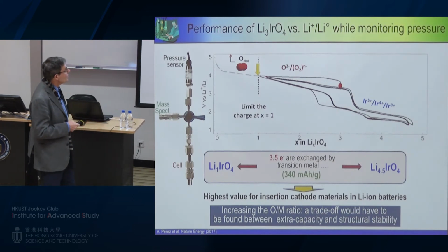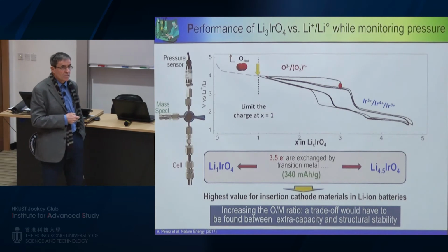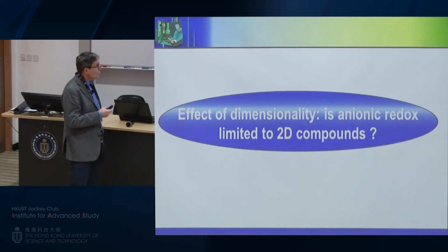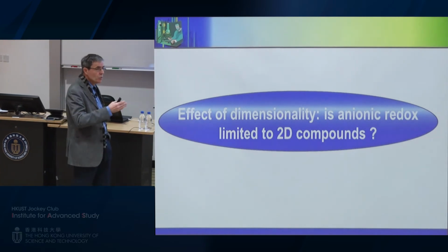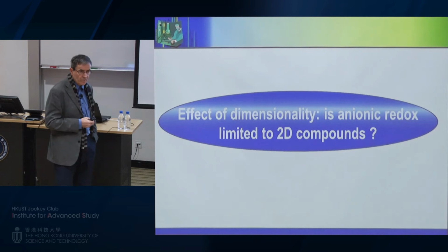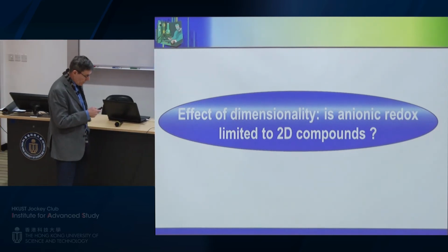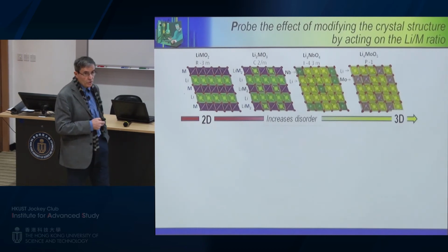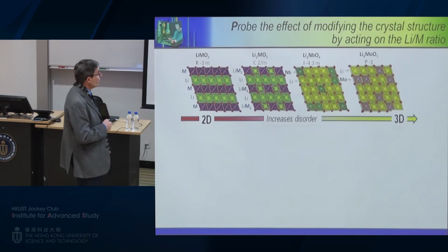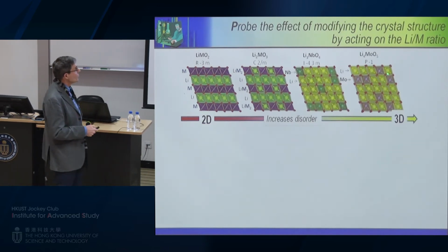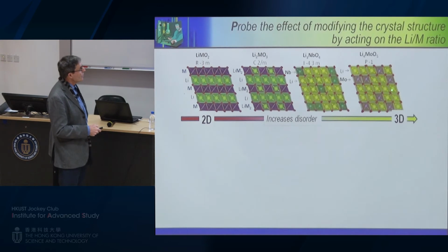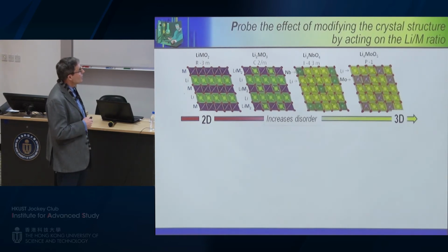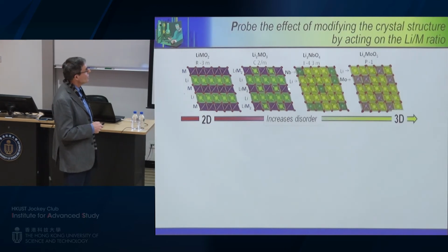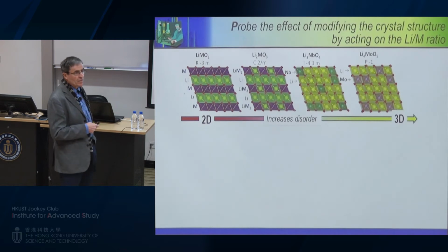So if you look at all of this, so far, I was telling you about materials that are layer compounds. So the question that you may ask is, is this new effect only specific to layer compounds? So again, we try to answer this question, and as a matter of fact, we were not the first to answer this question, because Yabuuchi has been trying to play this game, where he tried to move to this type of structure by nearly creating the rock-salt type structure, where by increasing the ratio lithium over M, he was able to obtain this disordered rock-salt structure that you can see here, disordered, because look here, you have nearly layers, and now you have a huge amount of intersite mixing.